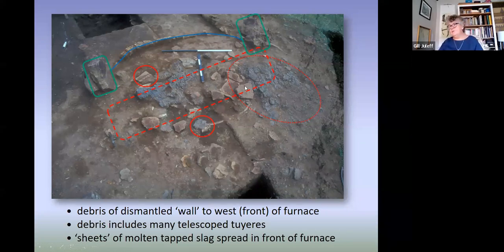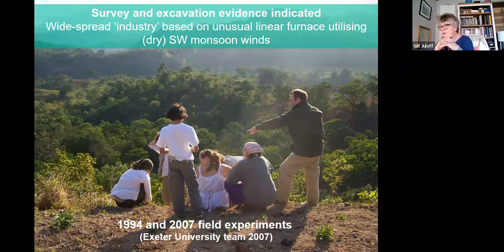Okay, so moving on from the excavation and the survey, the evidence that came from the survey and the excavation was strong, convincing, told a very good coherent story. It demonstrated a widespread industry across this region with these multiple sites. All of these sites are based on this very unusual linear shaped furnace that was using the dry southwest monsoon winds. That was all very convincing from an archaeological point of view.